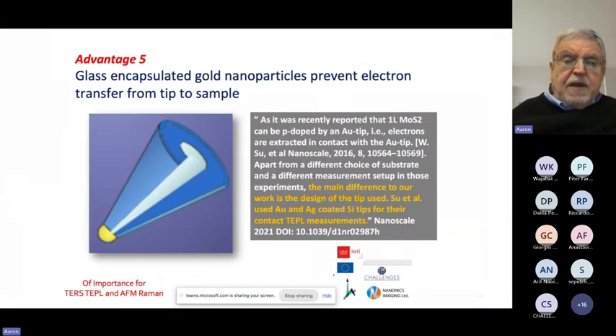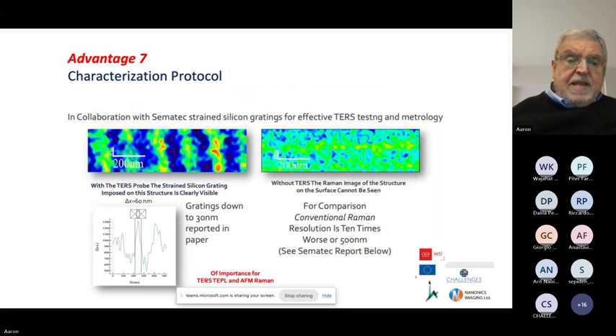Also, it has been found that if you don't encapsulate the gold in glass, then you start seeing electron transfer when you bring these tips very close to the surface. And that's another advantage to using such probes. In collaboration with Sematec, we have gratings that were made by Sematec of strained silicon on silicon. This is a 60 nanometer grating. And in the far field, you don't see anything, but you need a plasmonic probe in order to see it.